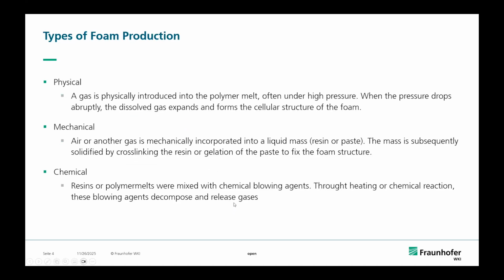So if we look at foams, we have in general 3 different types of foams. One is made physically, so the gas, the bubbles you have in the foam, are introduced in the polymer melt, which is pressed under high pressure, and then when the pressure drops abruptly, the gas expands, and then you form the cellular structures. You know this maybe as polystyrene. This is an example for it.